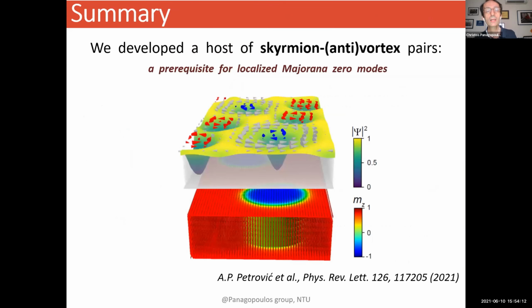So to summarize, I have shown you that we have finally been successful in developing, for the first time, a host of skyrmion anti-vortex pairs, where you can have magnetic skyrmions in the magnetic multilayer coupling to a superconductor and creating this energy string of 2 topological defects with different order parameters, one magnetic and one superconducting. And this is, as I mentioned earlier, based on theory, and one has to look at it from now on, a prerequisite for localized Majorana zero modes.